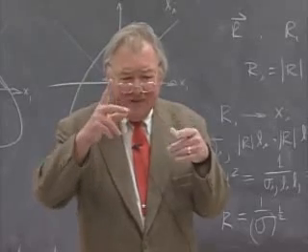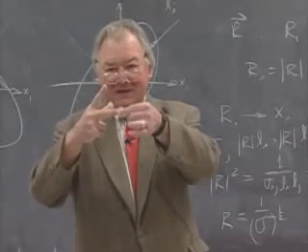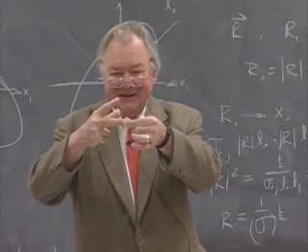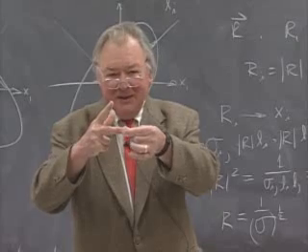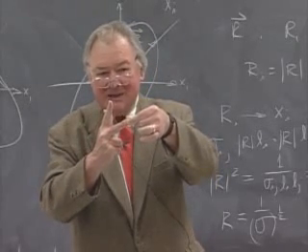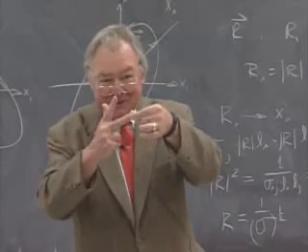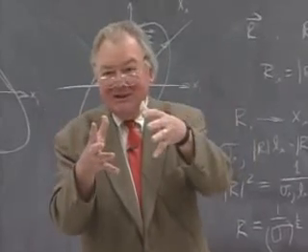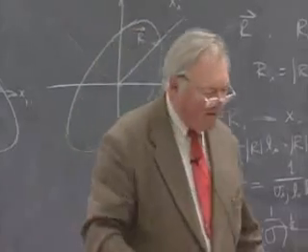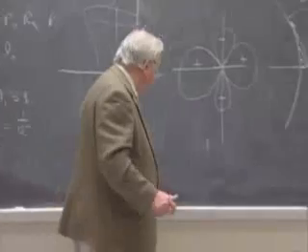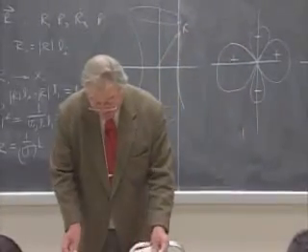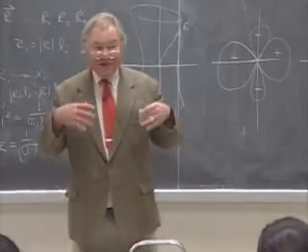These are tetrahedral frameworks in which one corner of a tetrahedron is dangling. And as you heat it up, this tetrahedral corner can get closer to other tetrahedra, which takes energy to do. But in so doing, you actually are changing the net volume occupied by the solid. So a very, very anomalous set of compounds. More of these have been found. There are probably a dozen materials now that have negative thermal expansion coefficients in all directions.